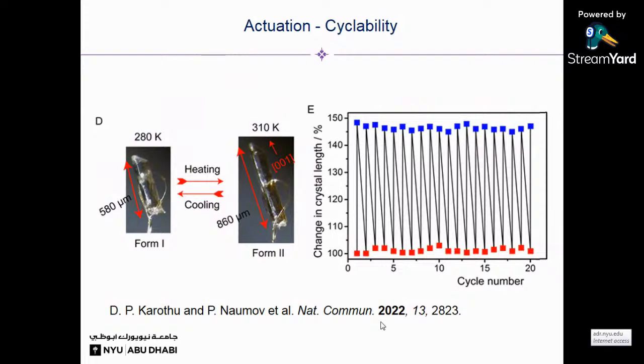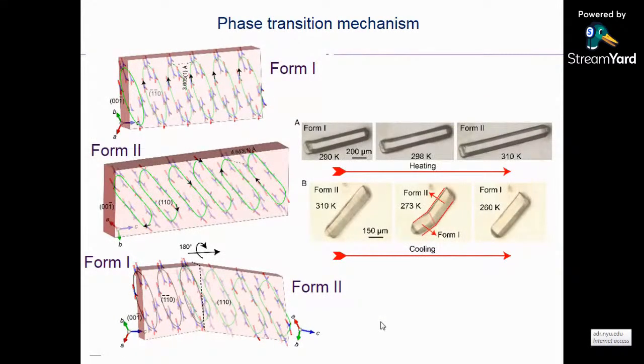You can do several cycles. We did several cycles. We don't see any change or deterioration of these crystals. And also these are reversible for several cycles. And this is the mechanism between both forms.